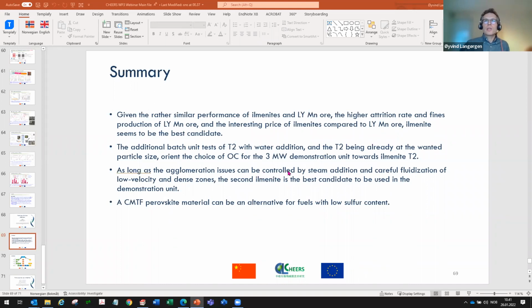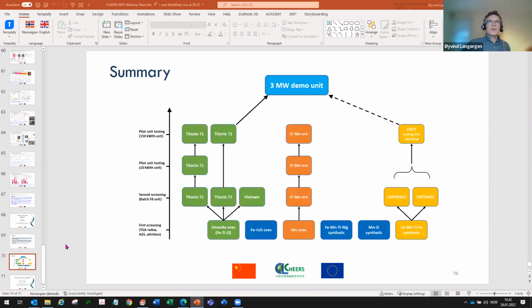So with careful fluidization of the systems, especially low velocity and dense zones like L valves, and steam addition, we believe this can be manageable. However, we have also seen that the synthetic material, the CMTF perovskite, is a really good candidate and can be an alternative for fuels with low sulfur content. At least we saw in the petcoke tests that it was deactivated by the sulfur content in the petcoke. So this is the summary repeated in a graphical way, nothing more.